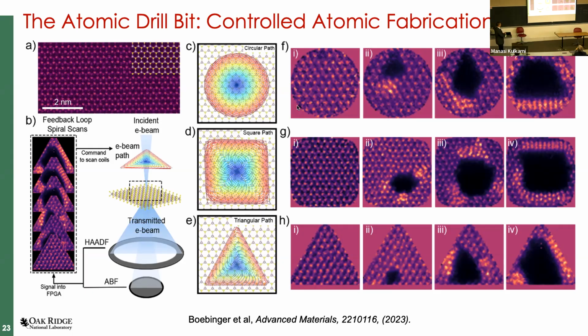If you cut it along different zigzag orientations or armchair orientations, perhaps this can give us another free space, like a little knob, to tune if we want to really controllably transform these materials at that scale. So in this case we came up with 3 different design paths: a circular scan, a square raster scan, and even a triangular scan. So these are some of the results.